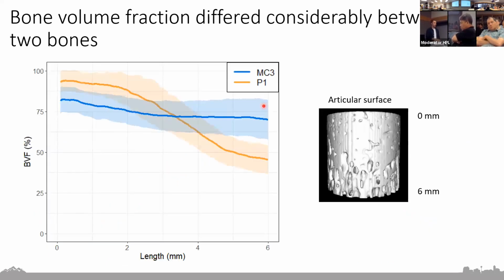So here we plotted the bone volume fraction as a function of the length of the sample, whereas 0 millimeters on the x-axis corresponds to the articular surface, and then 6 millimeters is deeper into the trabecular zone. And we found that third metacarpal, which is plotted in blue, had a pretty consistent bone volume fraction throughout the sample, whereas the P1 was a much more heterogeneous sample in terms of the bone volume fraction.